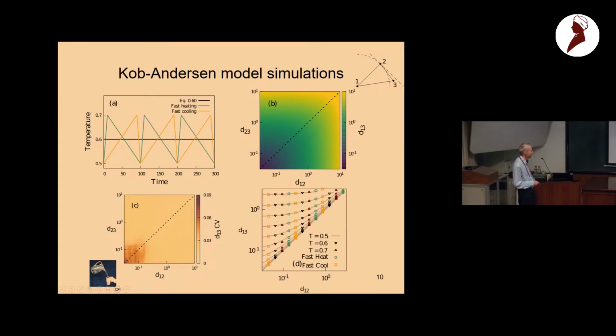Another way of plotting this is to look at, let me see. So this is D13 as function of D12 for a given value of D23 distance. And then we have equilibrium data and we have aging data, and they all collapse on the same curve. So this confirms that it's the same movie going on, whether we are in equilibrium or whether we are aging. We are on the same curve. The relation between the distances for a given 2, 3 is exactly the same in equilibrium and out of equilibrium.